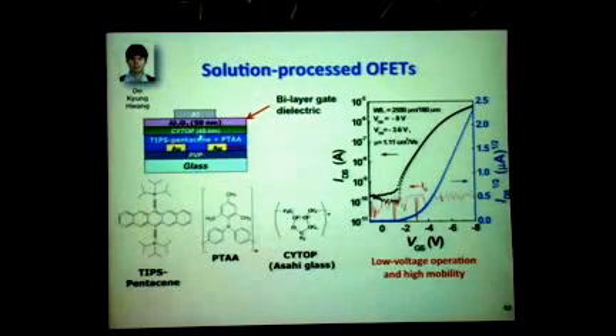Here you see the cross-section of this transistor. You have a substrate, bottom source and drain electrodes, a semiconductor layer spin-coated on top of these electrodes, and then your gate dielectric and top gate electrode. The conduction channel is at the interface between the semiconductor and the gate dielectric, so you can modulate the current flowing between source and drain by applying a gate voltage. Here's a typical transfer characteristic of a transistor like this, with average mobility values of the order of 1 square centimeter per volt second.